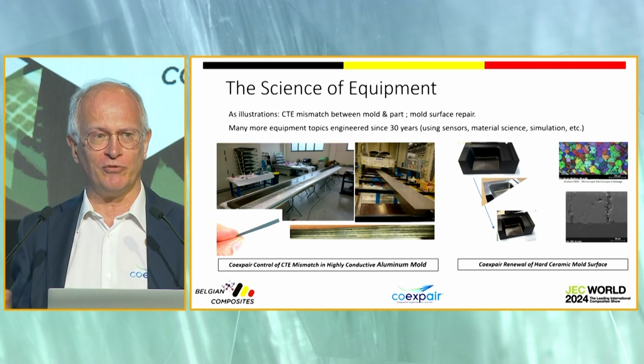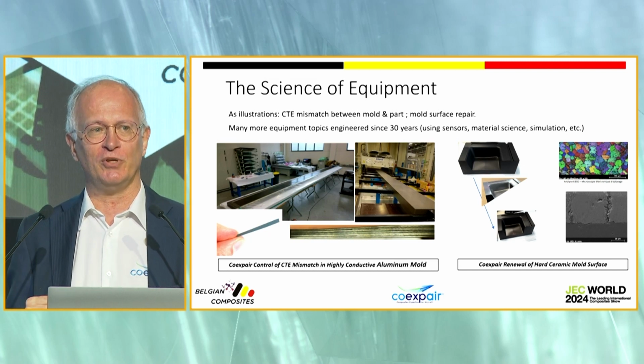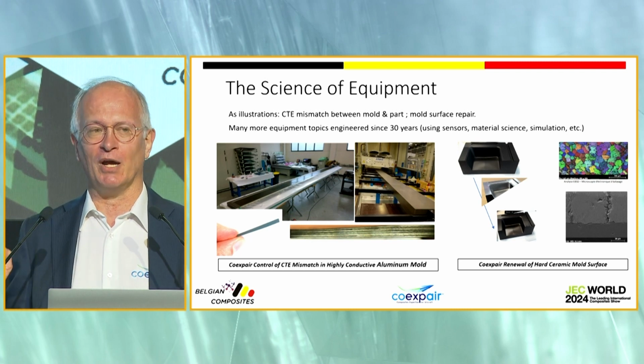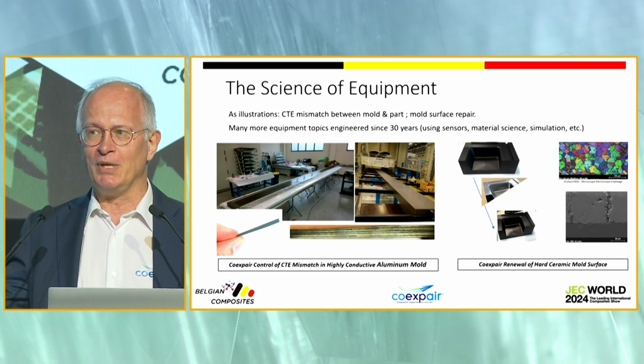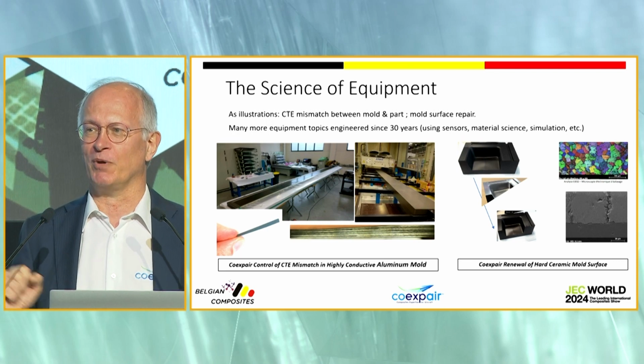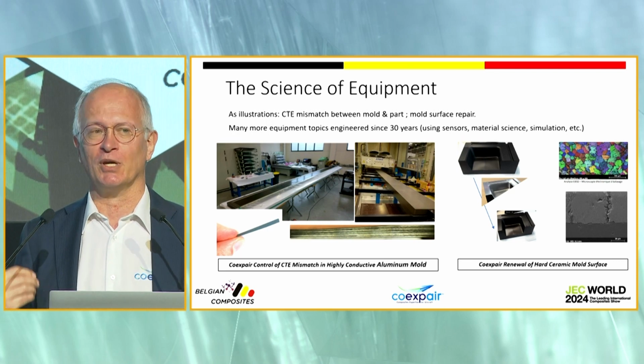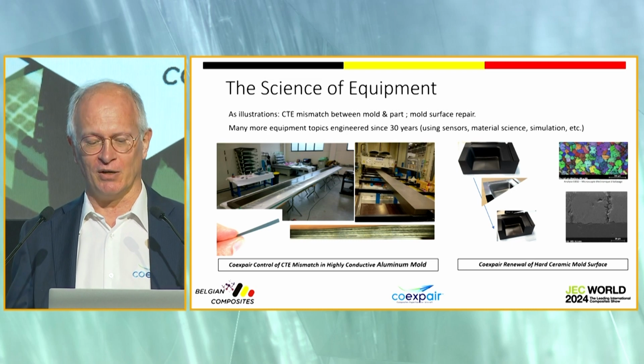You see here an illustration of an 8-meter long UD part in tape. When the mold expands, the aluminum mold will expand by 2 centimeters. The way the laminate moves is somehow pulled through that. With the tool expansion, we can control it, we can predict it. So we don't need INVAR.